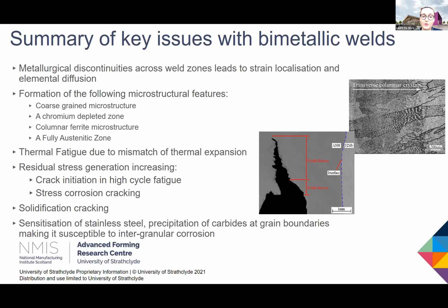You can also have thermal fatigue due to a mismatch in the thermal properties, and you can generate residual stresses in the joint, which can lead to crack initiation from high cycle fatigue or increasing the likelihood of stress corrosion cracking.